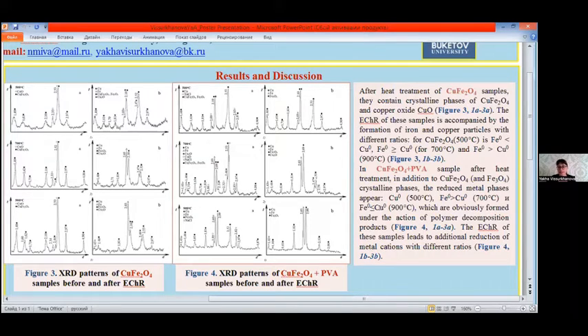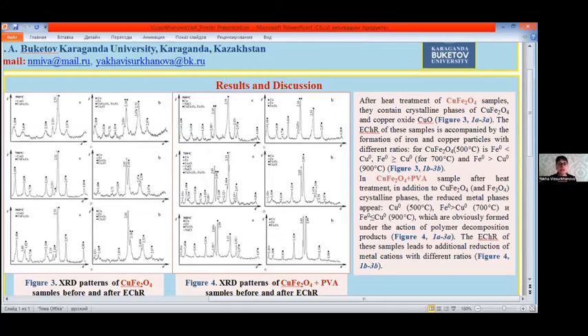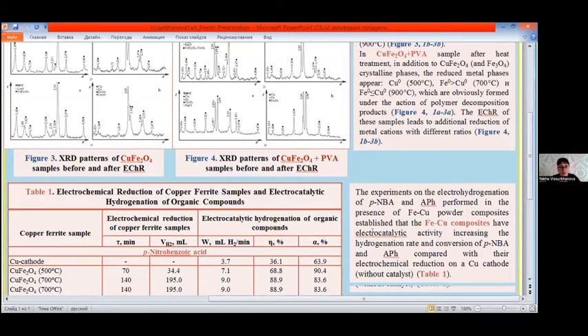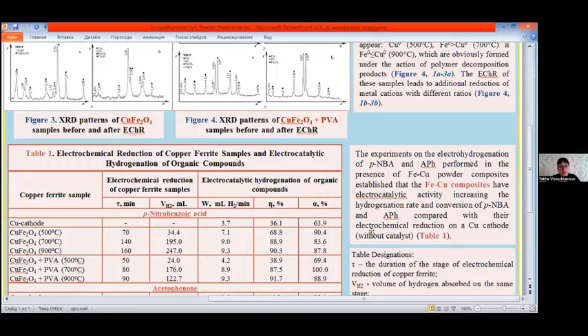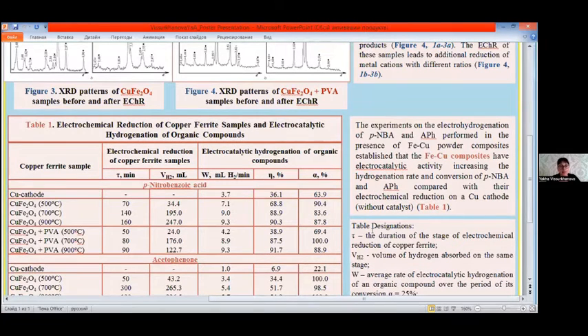This leads to the next point, which is that the thermal treatment of copper ferrite samples synthesized in the presence of the polymer is accompanied by metal reduction. This process is facilitated by polyvinyl alcohol decomposition products adsorbed on the surface of precipitated metals. The table shows results of electrocatalytic hydrogenation of organic compounds on the iron-copper composites as electrocatalysts.